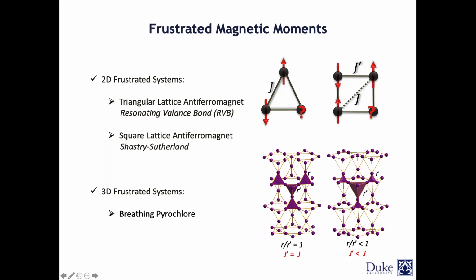Now, imagine if you start to change the symmetry, lower it, in a case that, for example, the down tetrahedron is going to be much larger than the up ones. So in this scenario, the first thing that happens is that the symmetry is now lowered, which later on I will explain why it is important. And R and R prime are no longer equal.